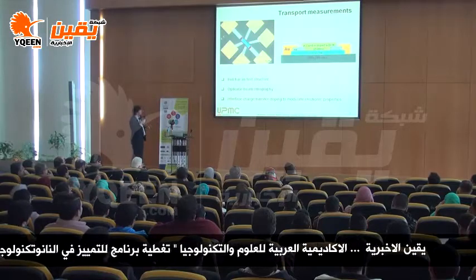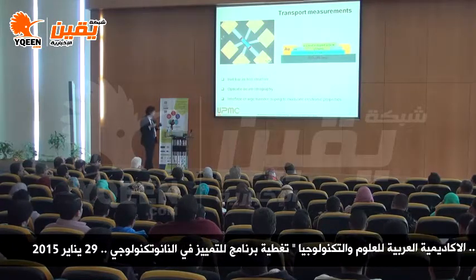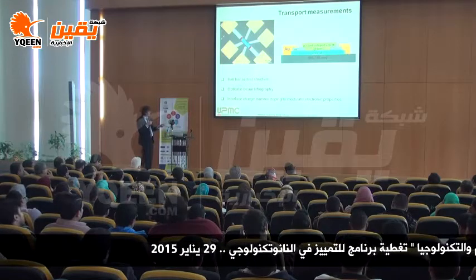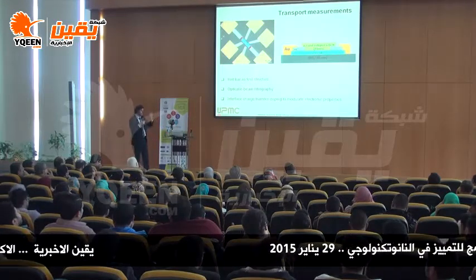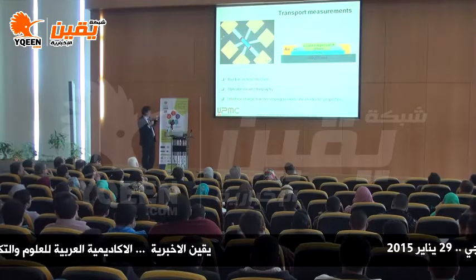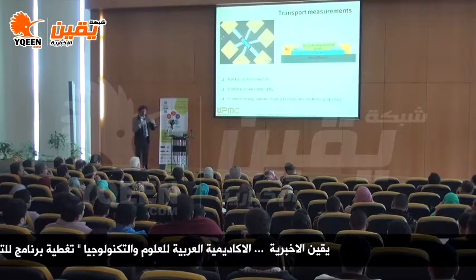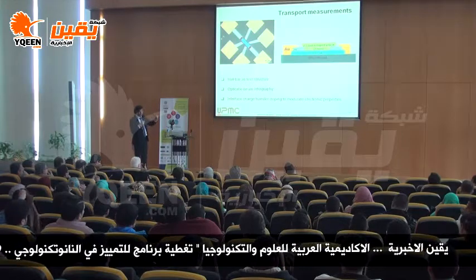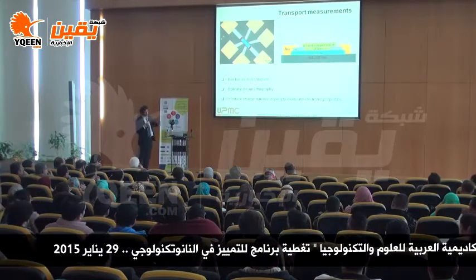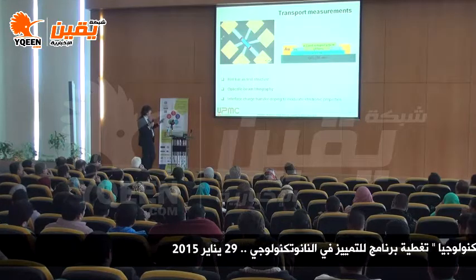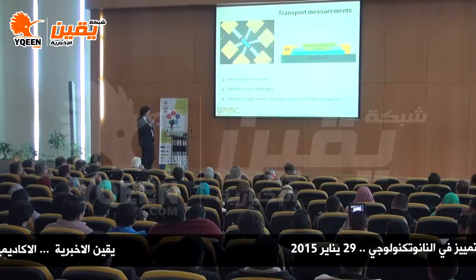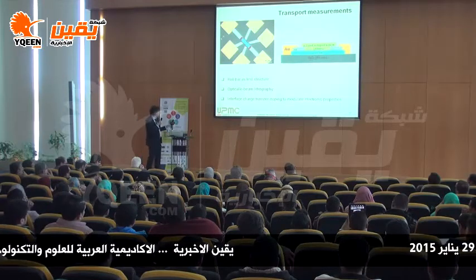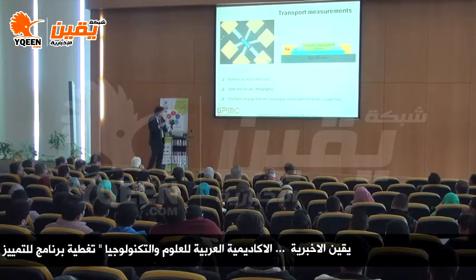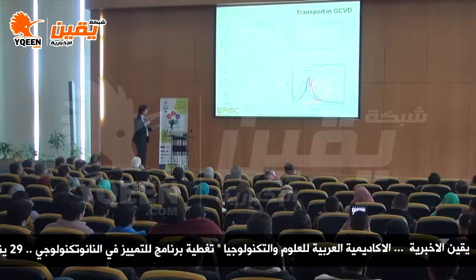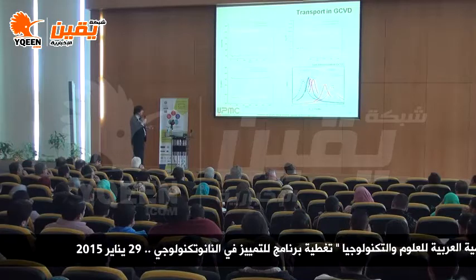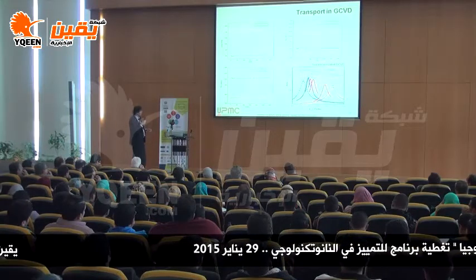Another piece of work here is to measure the transport properties of the graphene, but here we do it on amorphous silicon. Either we cap it or we put the graphene onto amorphous silicon to be able to characterize the graphene and see whether there is charge transfer, in other words, doping from the amorphous silicon that will be part of the solar cell and the graphene that will be the transparent electrode. So we devise typical Hall bar test structures, a few micrometers wide, that can be done either with optical lithography or even e-beam lithography. And then we measure a set of properties: the mobility versus temperature, the carrier density, the sheet resistance, and also we look at the IVs.